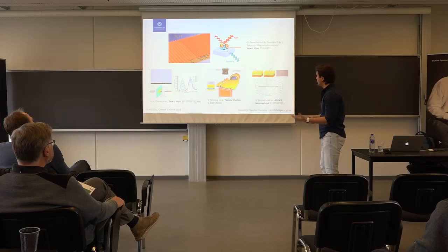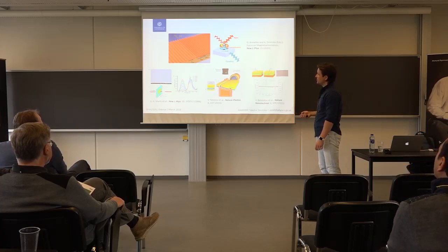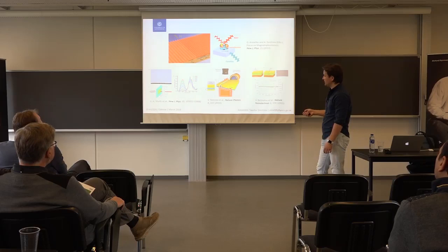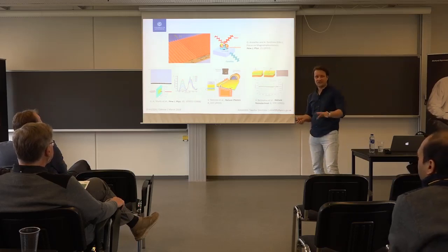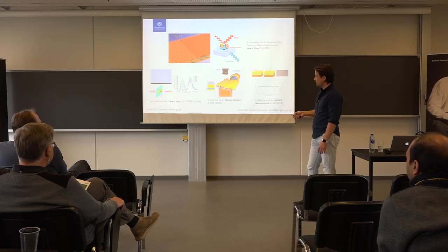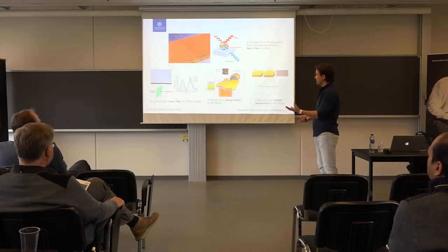There are several examples of how people combine that over the years. You can, for example, change the transparency of this kind of array where there are holes. So here is gold, and here is the magneto-optical active film. When you measure the transparency and you apply a magnetic field, the transparency is actually changing depending on which field you're applying. Here in millitesla, you already learned fridge magnet, 10 millitesla, good scaling, here 40. So again, applying quite low magnetic fields, you can play with the transmittance in this kind of arrays.